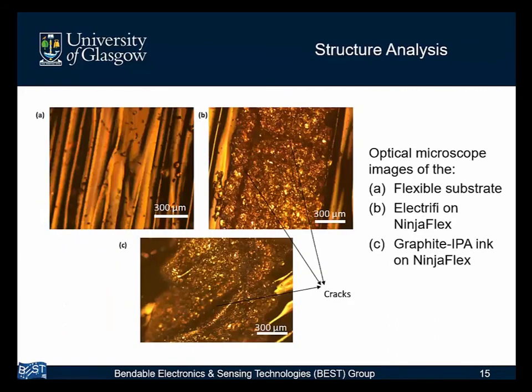In terms of going a bit deeper and looking at what's actually happening on the surface level of the substrate as well as the conductive materials themselves, we also haven't come across any research that looks at these types of materials in this use, as well as the use as bendable interconnects. So we're looking at the optical microscope images, and in A, we look at the flexible substrate itself, the TPU. In B, we look at the electrifi on the NinjaFlex, and on C, we look at the graphite IPA conductive ink on the NinjaFlex itself.